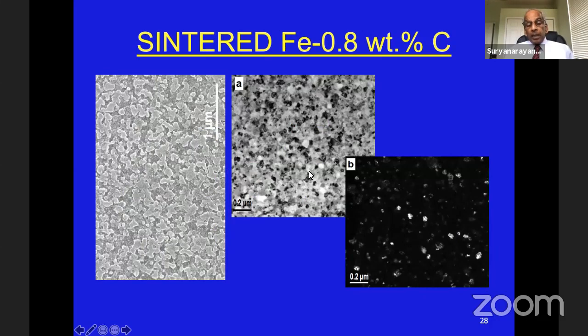But if you go to the transmission electron microscopy studies, you would notice that you have, again, alpha iron, that means the ferrite, and cementite. But if you have a pearlitic type of composition, that means 0.8 weight% carbon, you normally expect to see the so-called lamellar structure, the eutectoid lamellar structure. You don't see them. You see essentially equiaxed, very fine grains. The micron marker is 0.2 micron. This is only about less than 50 nanometers, even after consolidation.